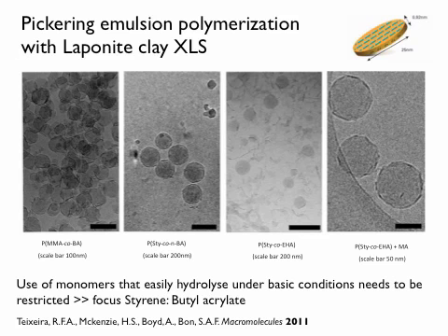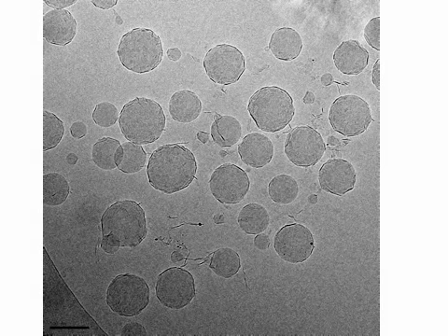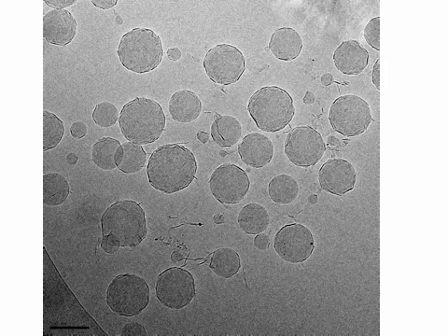which is a nice material to play with. So in order to solve this, if the particle is too hydrophobic, you can add a little bit of a hydrophilic co-monomer. If you add a tiny amount of methacrylic acid to this emulsion polymerization recipe, then all the platelets are around the particle. So you've solved your problem. So cryo-TEM, in this particular case, is very, very useful to look at. And here you see just another image showing the same thing. You can beautifully see that these clay platelets decorate very nicely over the particles.